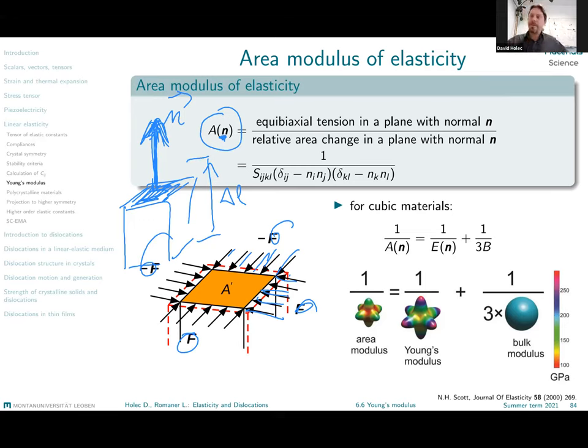It can be shown that for cubic materials, this area modulus of elasticity is related to the Young's modulus in a direction perpendicular to this plane, and the bulk modulus. Bulk modulus is the elastic response of a material to an applied hydrostatic stress. Therefore, the spatial distribution of the area modulus is going to be the same as the spatial distribution of the Young's modulus, simply because the bulk modulus is a quantity which is directionally independent.